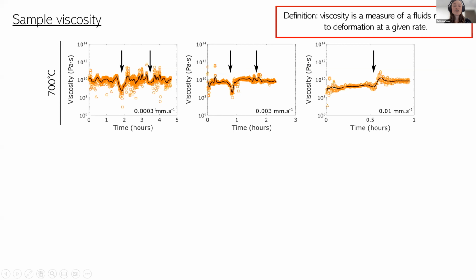And basically, the lower the viscosity, the easier it is to deform and the weaker the substance is. And you can see that when we're pushing the rock at a very slow rate, you see these massive drops in viscosity as you go through both transitions. But this drop disappears, or it's less significant, as you push at a faster rate when you're deforming. So clearly that is a transformation weakening process that's occurring during this quartz to coesite transition, but it's rate sensitive.